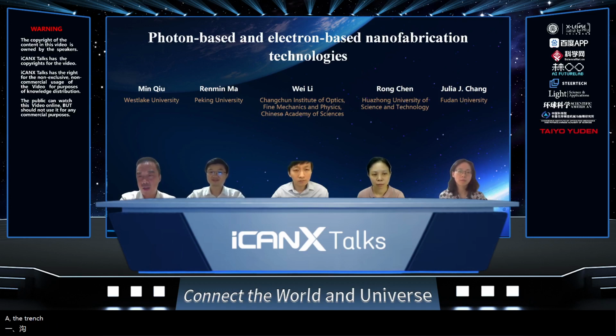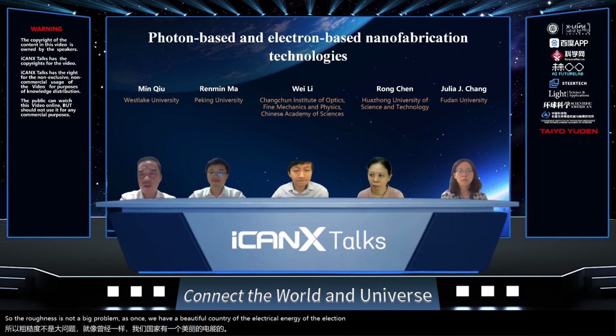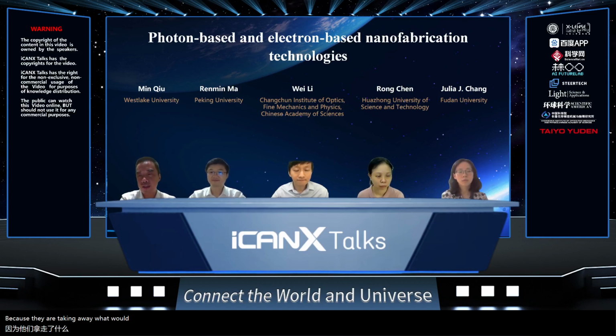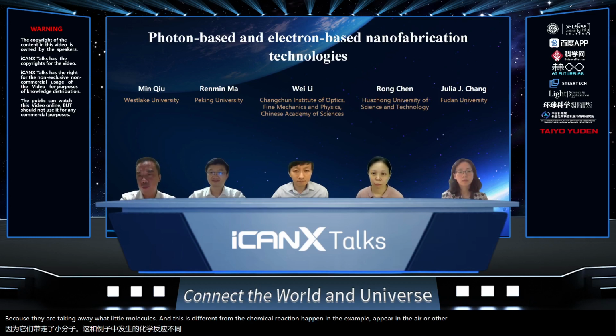out of this ice. So for example, we can make a 30 nanometer gap in 600 nanometer thick ice. So it's already a 20:1 aspect ratio. So the roughness is not a big problem as long as we have a beautiful control of the energy of the electron, because they are taking away more water molecules. This is different from the chemical reaction happening in, for example, PMMA or other e-beam resist.